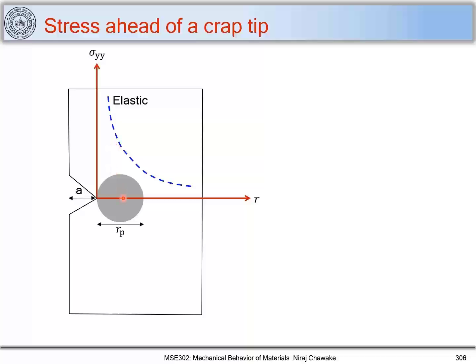Now let's consider we have a plastic zone which has a diameter of Rp ahead of this crack tip. This will happen when the material deforms plastically, or the material is plastic or ductile. So for this kind of material which shows a plastic zone ahead of the crack tip, the stress variation will be sigma y, where sigma y is nothing but the yield strength of the material. So the stress ahead of the crack tip remains constant, and such kinds of materials are called elastic plastic materials. And when this plastic zone ends, the stress decreases in this fashion with respect to r.